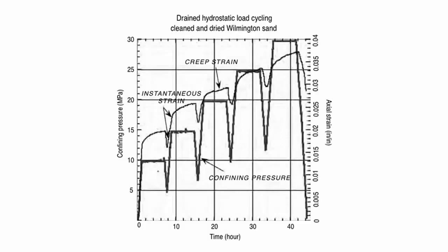The sand was placed in a jacket in a bath of water, the fluid pressure was pumped up, and then the strain was measured. You pump up the fluid pressure, hold it fixed, and measure the strain. The fluid pressure is being held fixed here, and the material continues to strain.